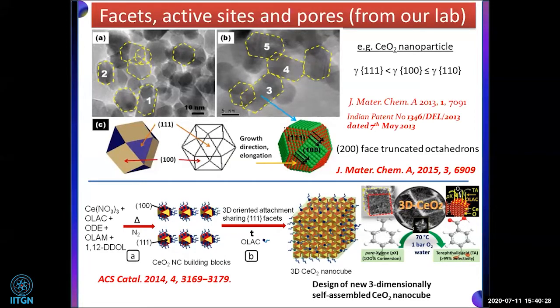After getting that experience, we came to the next work, where we prepared new three-dimensional self-assembled cerium oxide nanocubes. What is the purpose of that? We started with cerium nitrate, oleic acid and oleylamine. When they make the nanocrystal building blocks, the tiny nanoparticles of cerium oxide are around 6 nanometer in diameter. From this experience, they are mainly 100 and 111 facet terminated nanocrystals.